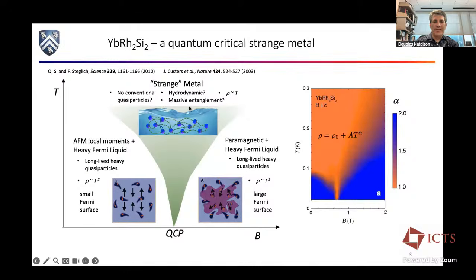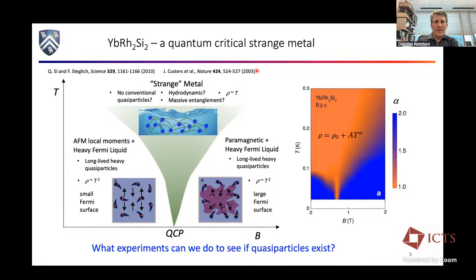I do want to say one thing. The experiments we're doing, and there are technical reasons why we did it this way, and we are very interested in the future in going down into this temperature regime where you can really see the field-tuned crossover from the Fermi liquid to the non-Fermi liquid, or the strange metal to the non-strange metal. But everything I'm going to show you on the experiment side was done at warmer temperatures up here, where this quantum critical fan is essentially expanded to fill all readily laboratory accessible magnetic field space. So everything I'm going to show you was in the strange metal regime.